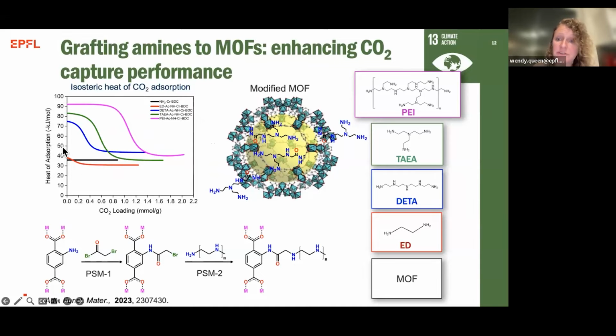These are pretty much in the physisorption regime. Now, when we look at materials with high densities of primary amines, what we see is an increase in the binding energy up to the polyethylene amine. We can see that it goes up to about 90 kilojoules per mole, which is in the range of chemisorbents.